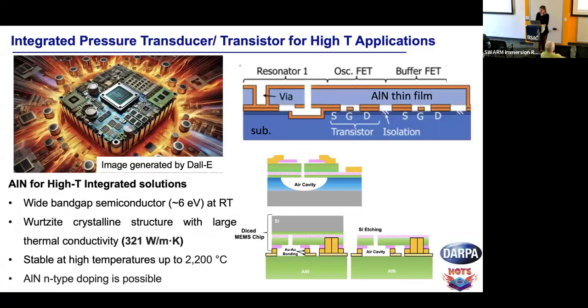So that's a great question. You're asking if the temperature is going to swing or if the temperature is constant. Basically, the requirement for this DARPA project is that we're at 800 C and it's not changing at all. However, if the temperature also changes, there are a couple of ways that you can account for that. One is to have a reference oscillator that doesn't move with pressure, but only moves with temperature. So you can calibrate out the impact of the change in the temperature in your frequency shift.